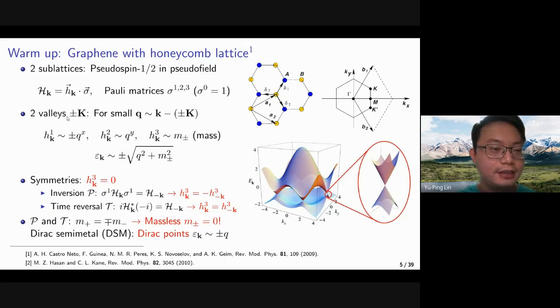And if we look at the values, we'll find that if we have both inversion and time reversal symmetries, we will have the mass to be either negative or plus equal between the two valleys. And it also means that we should have a massless condition, which corresponds to the vanishing of the third component. And this means that graphene will have Dirac points at K and minus K, with a linear dispersion. And this makes graphene a kind of Dirac semimetal in two dimensions.